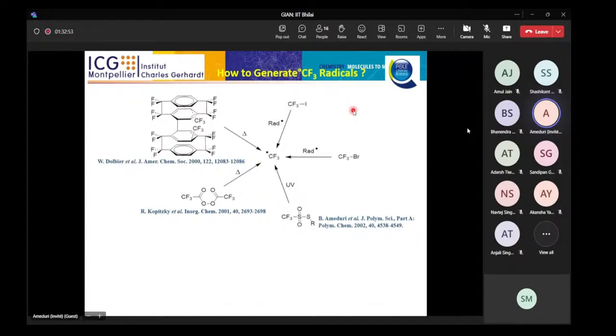If you have the end group which is known, you can access this molecular weight. And indeed, from the literature, we know that the CF3 radical can be generated by different systems. This can be made by telomerization, which we'll discuss later, by this iodo paraffin, this peroxycarbonate, this thio sulfur compound, and also CF3Br, but this doesn't exist anymore. This was published at least 30 years ago.